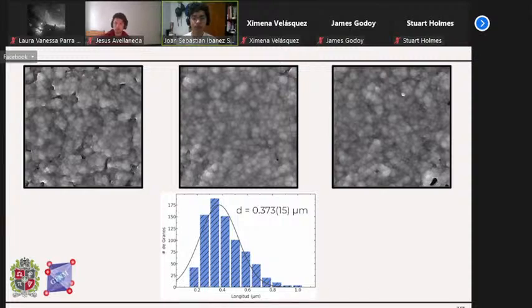These three photos are three different composition points that we took with the scanning electron microscope. After the last process in the oven, in general, we see that the shape of the grain is almost spherical, as is normal in solid-state reaction processes. And the grains in this case seem to be trying to stick together. They are trying to fuse, which is, again, normal in solid-state reaction. Since we saw from the histogram that there was only one relevant grain size, with only one clear peak, we can rule out, for example, several magnetic phases or a high impurity content.